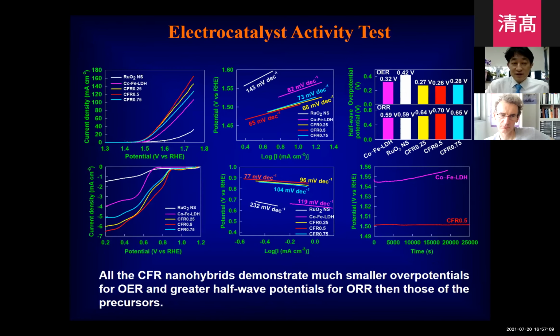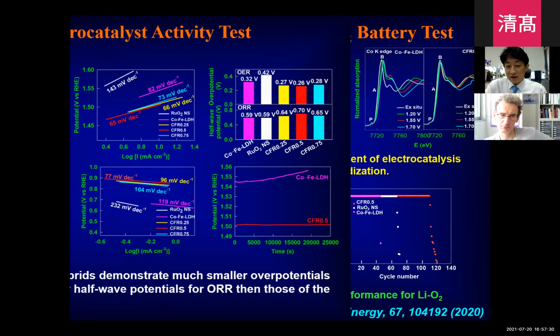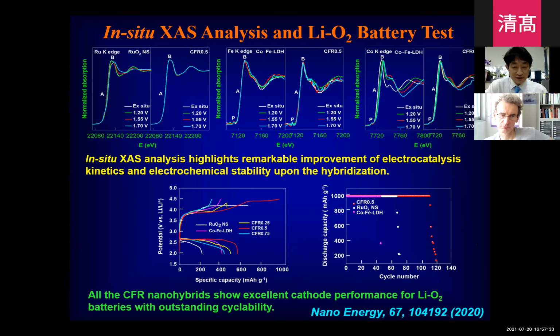So we applied the resulting hybrid material as an OER catalyst and ORR catalyst. As you can see here, such intimate coupling is effective to enhance the OER activity and the ORR activity. So we used this material as the electrode for a lithium oxygen battery. As you can see here, we observed a remarkable enhancement of the electrode performance of the LDH during the hybridization with the ruthenium oxide.